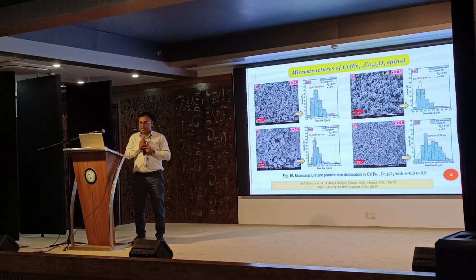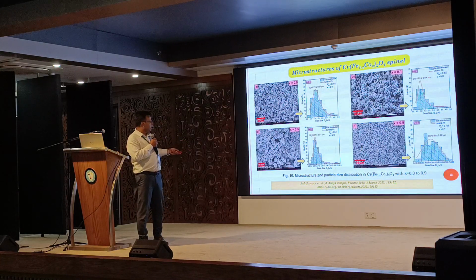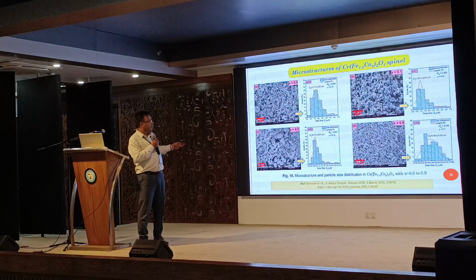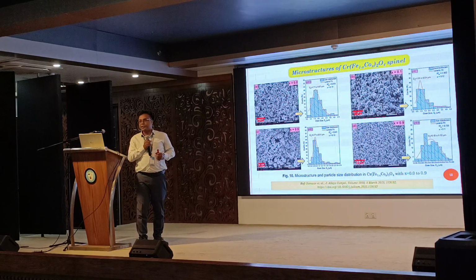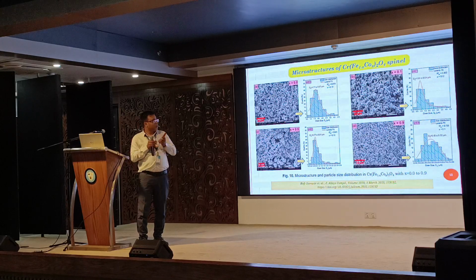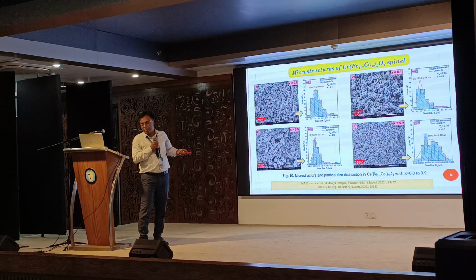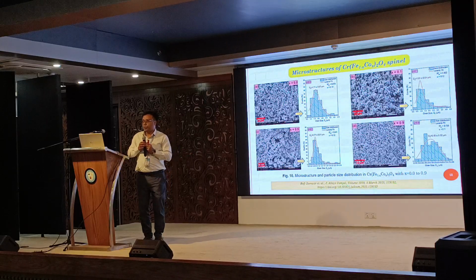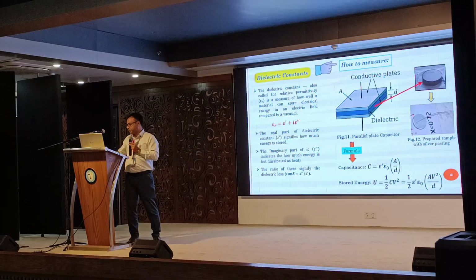So I am showing here the grain size. The microstructure is showing we have improved the sample grain size. How did we improve it? Whenever we doped the materials and heat treated them, the size of the materials decreased, and we have reached up to 500 nanometers, and hopefully we will reach the nano level.